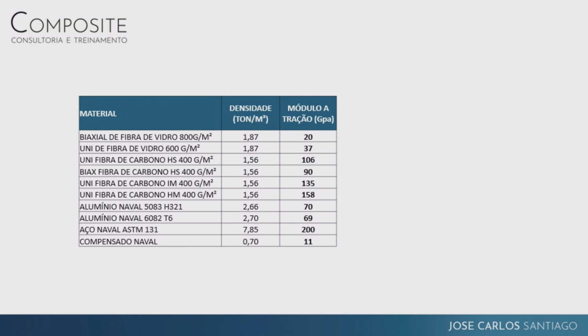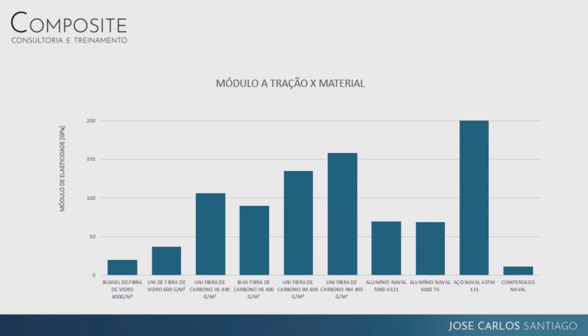We go to the elasticity modulus. We have traction, compression, shearing, stress, fatigue. I would need three time slots, and we would end around 4 p.m. The elasticity modulus in traction, even the glass fibers have a reasonable modulus. When it's carbon fibers, unidirectional, these moduluses are very high compared to aluminum. They're higher and very relevant compared to naval carbon steel, ASTM A131. It's a classified naval steel. So large vessels use that kind of material. So we see that the carbon fibers have a very high performance and they beat steel.